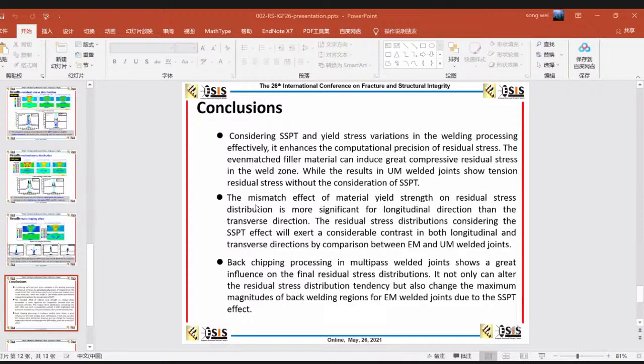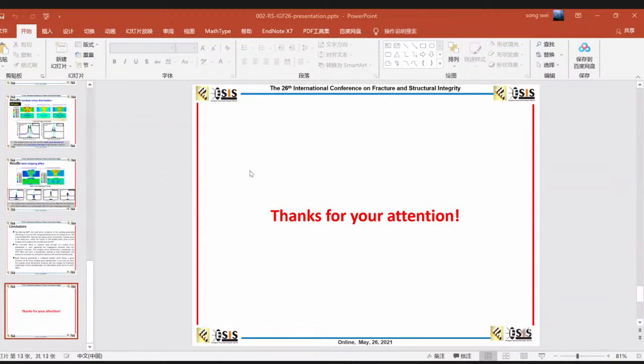The third conclusion is that the back chipping processing in the multi-pass welded joint shows a great influence on the final residual stress distribution. It not only alters the residual stress distribution tendency, but also changes the maximum magnitude of the back welding regions for the even matched welded joint due to the SSPT effect. Okay, thanks for your attention.